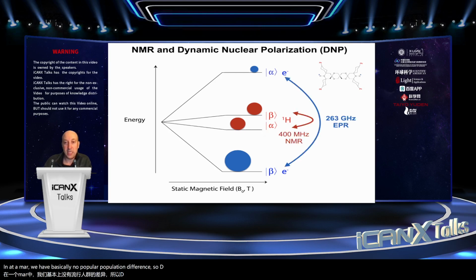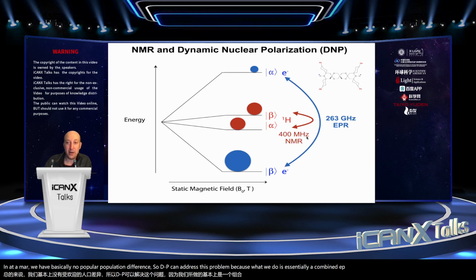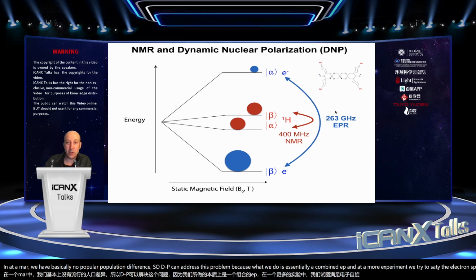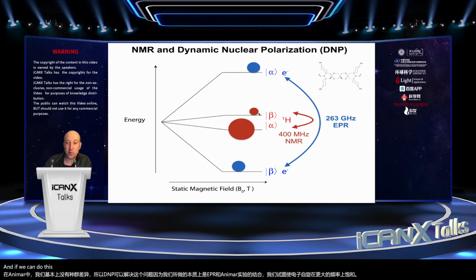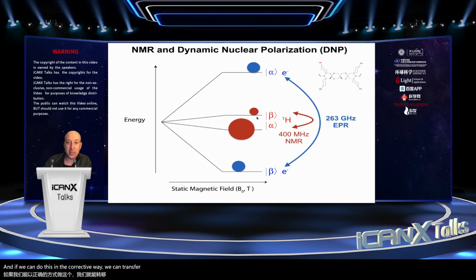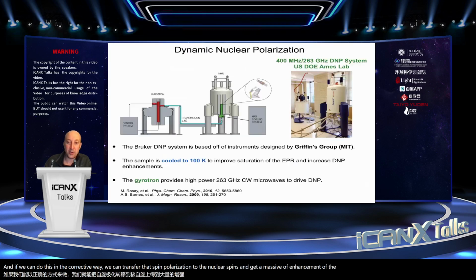So DNP can address this problem because what we do is essentially a combined EPR and NMR experiment. We try to saturate the electron spins at their Larmor frequency. And if we can do this in the correct way, we can transfer that spin polarization to the nuclear spins and get a massive enhancement of the NMR signal.